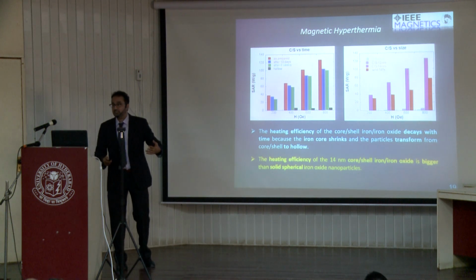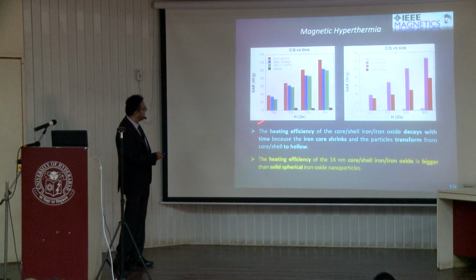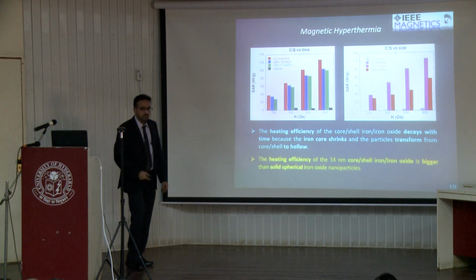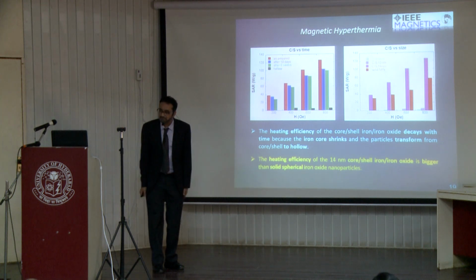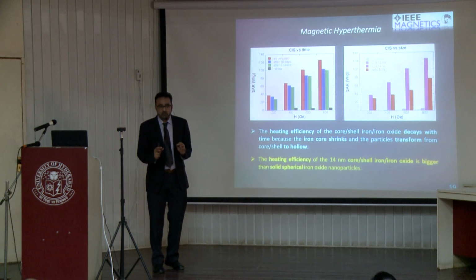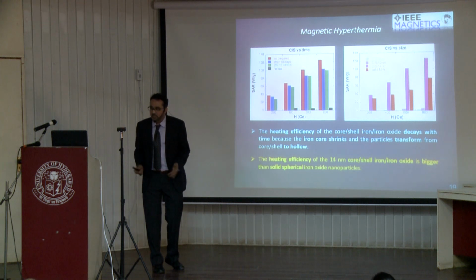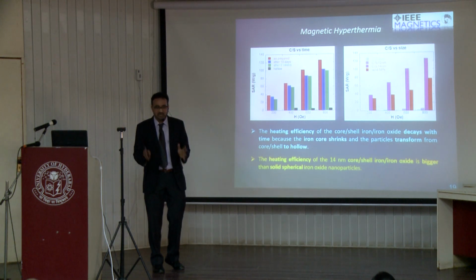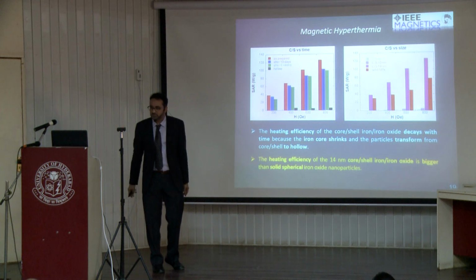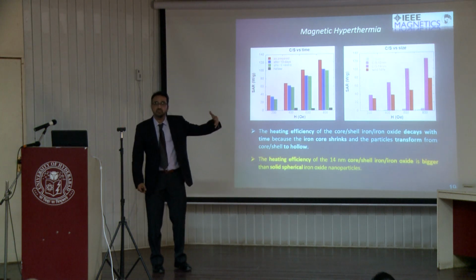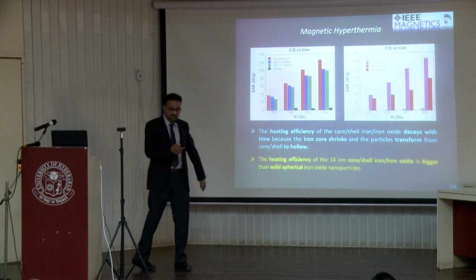However, our happiness was short-lived because of this Kirkendall effect. It starts degrading and eventually becomes hollow, and then hollow nanoparticles have no SAR. Okay? Well, the problem is that the time it takes is unreliable. We can't predict how long this will take for different systems. So it's not something that can be reproducible. So we have to toss this and move on to other ways of making these kinds of particles.